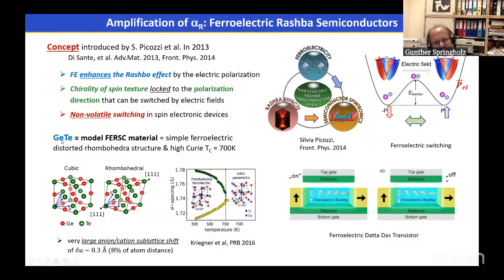She has proposed germanium telluride as a model system for these ferroelectric Rashba semiconductors. And germanium telluride is one of the simplest ferroelectric systems. It is shown down here. It basically has a rock salt cubic structure, which is slightly distorted along the 1-1-1 body diagonal direction. In addition to this distortion, the sublattices of the germanium and tellurium atoms are slightly shifted with respect to each other. And this shift is the origin of the ferroelectric polarization in this system.